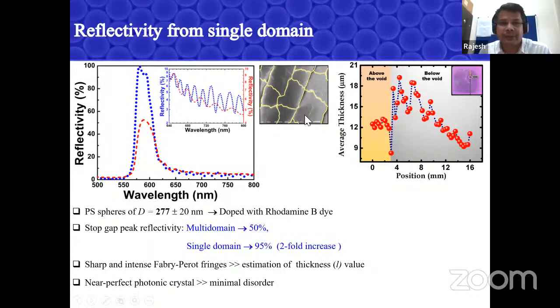We measured by looking at one spot on the sample, and the blue line is our measurement. You can see that it's nearly touching 100% reflectivity of light. The conventional measurement, which you see in the literature, and which we also did before having this setup, comes to closely 50-55%. So this kind of nice optical instrumentation can help you even though your sample is not that great, because your colloidal systems have less index contrast. So you can use it for many fundamental studies.